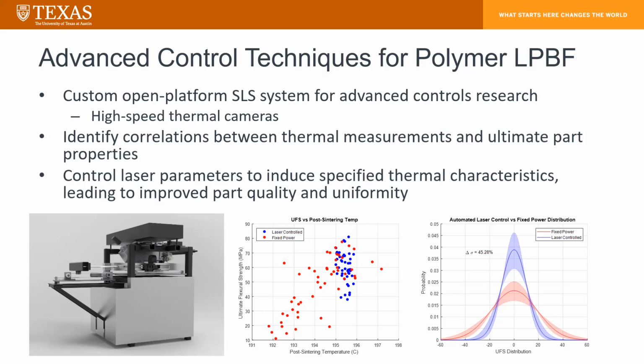And so we've taken that information and built a controller around that that can control our laser power to produce a much narrower range of these temperatures. And that's the blue data shown in the middle graph. And that results in a narrowing of our standard deviation of flexural strength as well. So using this method, we're able to create much more repeatable and much more uniform parts.